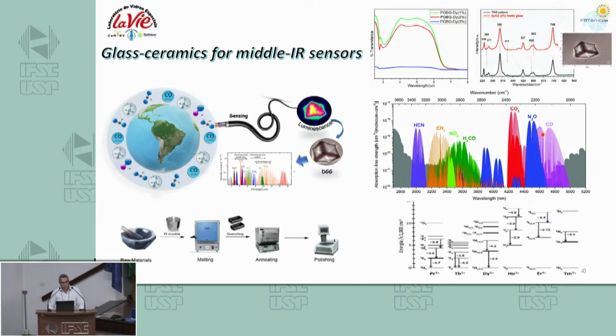So one possible application is to use these garnets, for example, to develop some sensors in the infrared. Nowadays, there is some chalcogenide glass doped with holmium that is used, for example, to detect CO2 or other molecules in the extraction of petroleum. The main problem is the emission of holmium inside glasses is broad. And the absorption of gases are many times very close to each other. So if you use crystals, we can make this emission much narrower, and then we can tune with more precision into this gas.